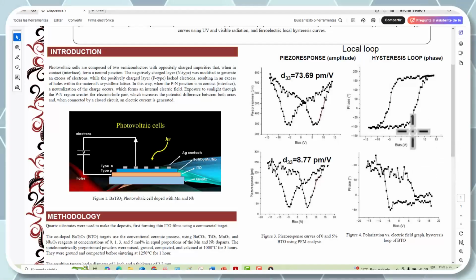Figure 4 determines the saturation polarization, remnant polarization, and coercive field of the sample set locally by the applied field. These results produce a phase shift of approximately 180 degrees due to the switching of the domains in the samples. The local saturation and remnant polarization values continue to decrease starting with the pure BTO.